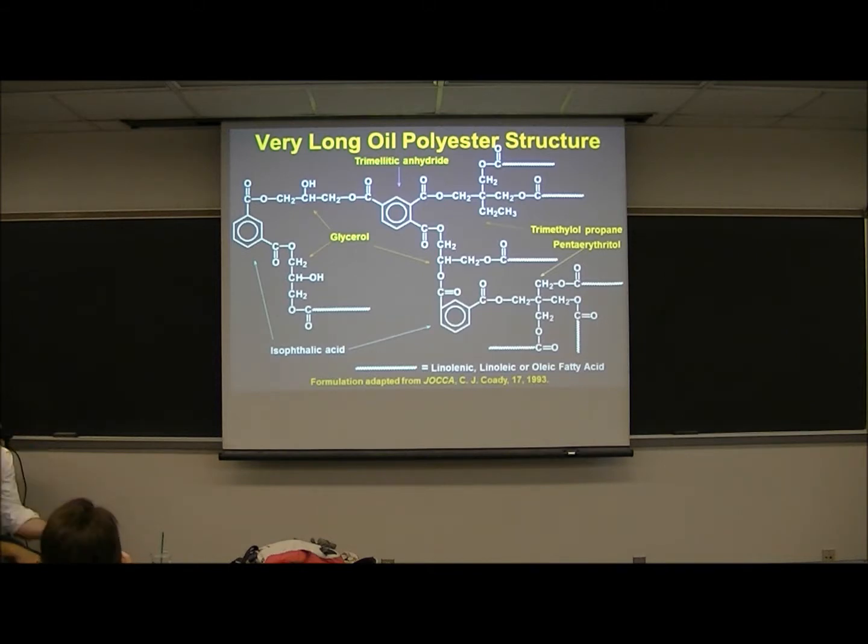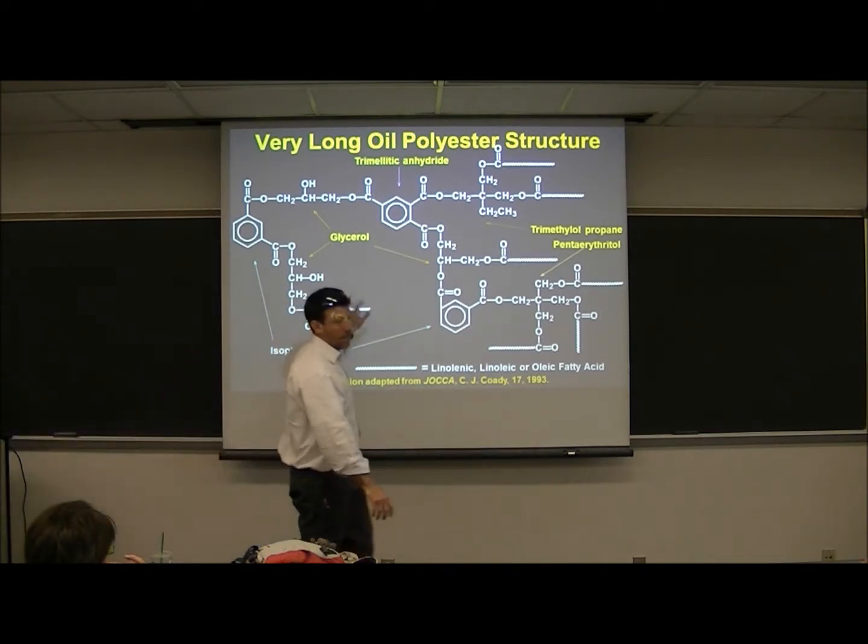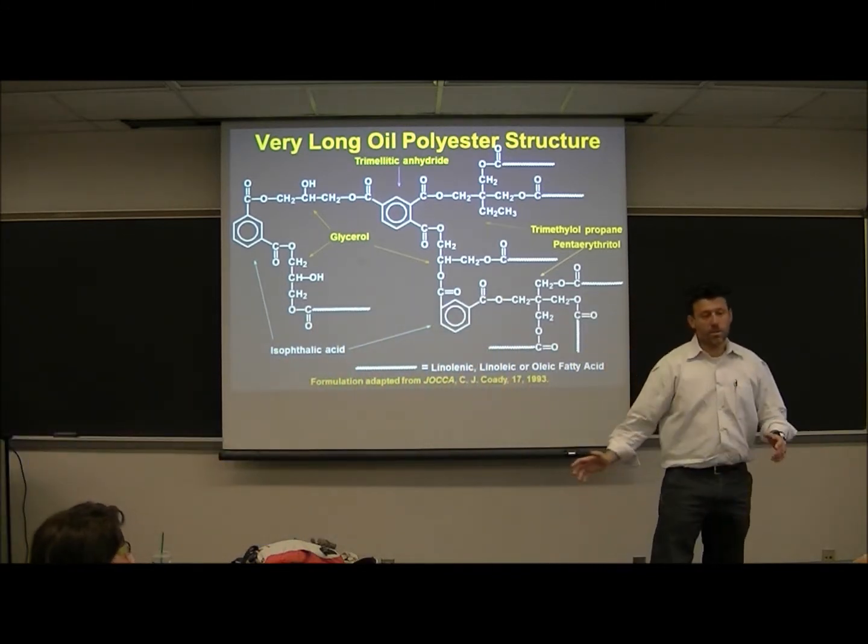Because as soon as you add the water, it swells. Then the coating goes through the process of going from a liquid to a glass, or a liquid to a non-tacky material. It might not quite be glassy, it could be leathery. But the coating is losing mobility as the rings are shrinking back down and water is being evolved. So as of right now, everybody that does use water-based only uses it after they have sealed the wood. People try it all the time. Don't get me wrong. We've tried it as well. We've taken oil-modified latexes and cast onto wood, and we still have the same problem.